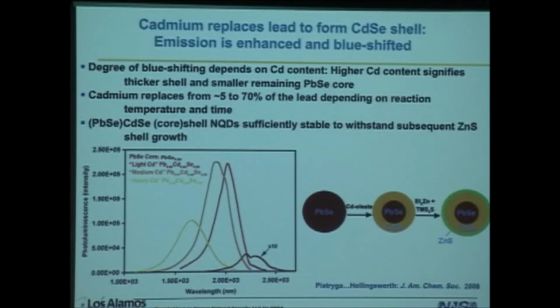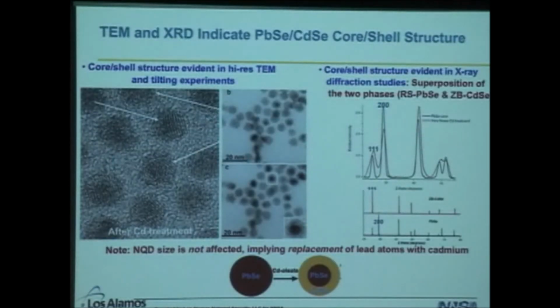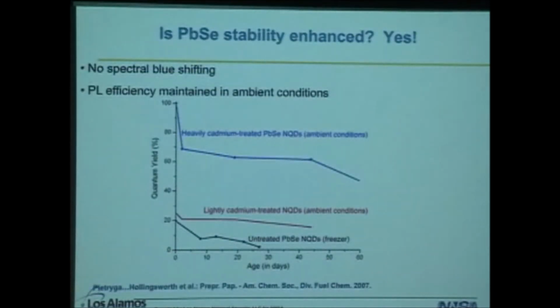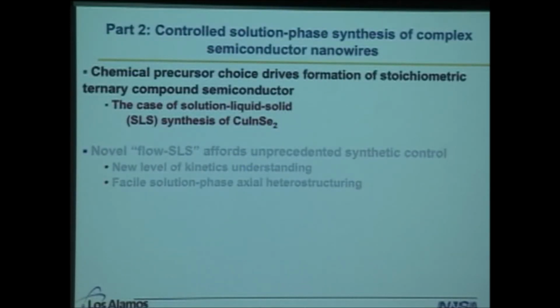Of course, this process results in blue shifting, but then you stabilize the particle with the shell, and the emission intensity enhances significantly. We did TEM and XRD to demonstrate the shelling. But clearly the stability is greatly enhanced. These are core-shell lead selenide, cadmium selenide quantum dots stored under ambient conditions, with relatively minimal quantum yield issues and no spectral blue shifting, whereas even if you store untreated quantum dots in a freezer in the dark, they will be down to 0 efficiency within a month. So that was a nice result.